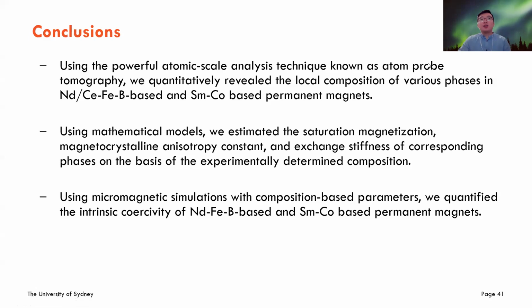For the conclusions, we use the powerful atomic-scale atom probe tomography, which can quantitatively measure the composition of the constituent phases, and also the segregation behavior in different types of magnets. Based on the experimental observations, we estimate three key parameters: saturation magnetization, anisotropy constant, and the exchange stiffness. Using these parameters, we construct the models for the simulation to bridge the microstructure and the magnetic properties of the permanent magnets.